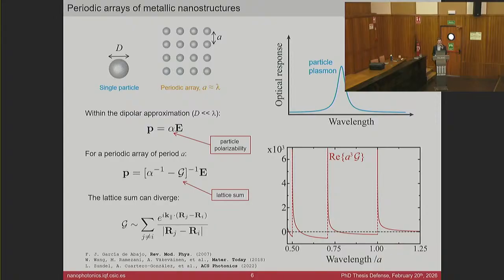This occurs only for certain wavelengths that are commensurate with the periodicity of the array. And in such cases, we have these kind of divergences that we know as Rayleigh anomalies, where the lattice sum attains arbitrarily large values. Now, in the same way that we can understand the plasmons as the poles of the polarizability of the individual nanostructures, now, when these two functions intersect, we are going to have a pole of this kind of effective polarizability of the array. And when this happens, a new resonance will arise, a lattice resonance, that is now a mode of the whole system, of the whole periodic array, because it encompasses both the response of the individual nanostructures and their interactions. And note that it can achieve a much narrower spectral profile, thanks to the fact that this lattice sum is really dispersive. So this intersection between these two functions occurs only in a really narrow spectral region.